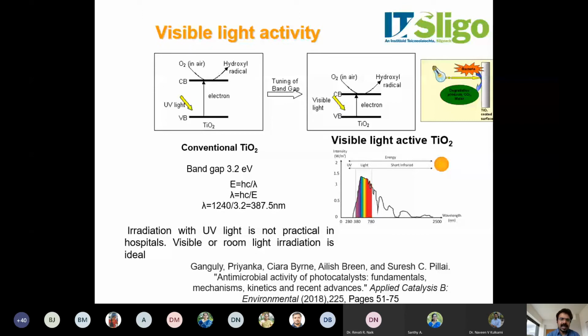What this means is that you need a wavelength lower than this to make the reaction happen, or you need an energy higher than this. So if you want to irradiate titanium dioxide to make the reaction happen, you need a radiation below 387 nanometers, which is in the UV region. So since the band gap of titanium dioxide is 3.2 electron volt, you need ultraviolet light to make the reaction happen. Is that feasible?